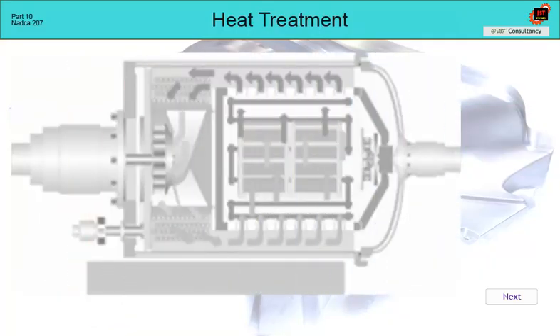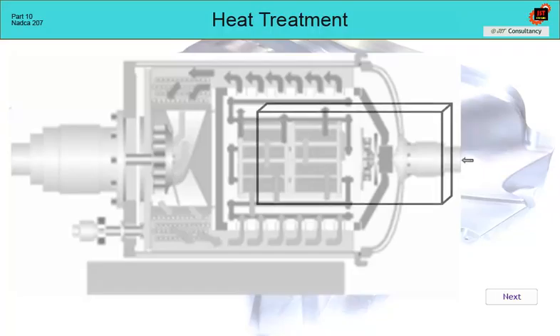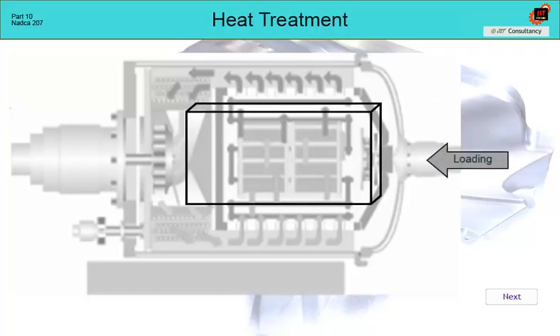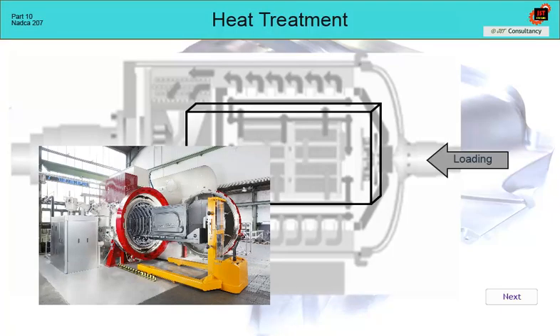If we place only one mold insert in the furnace, we insert the TS and TC thermocouples according to the previous instructions. The position of the insert should be as shown in the figure. That is, in the furnace axis, so that the largest irradiated surface is parallel to the heating wall. The reason is the uniformity of heating of the body, when part of the heat is transferred convectively from the flowing gas, but part by radiation from the heating elements.